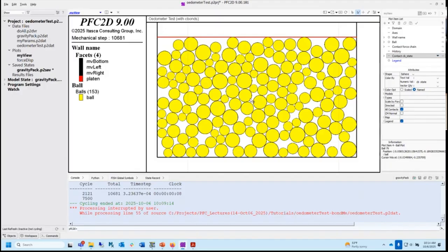We press it until it reaches a pressure we want, and typically we make that pressure low so there are no big overlaps. Then we tell it to bond everything within a certain distance, and it fills the gaps. So we have a controlled way of building a microstructure. That initial pressure and the installation gap are fundamentally parameters affecting the final material properties of the bonded system.